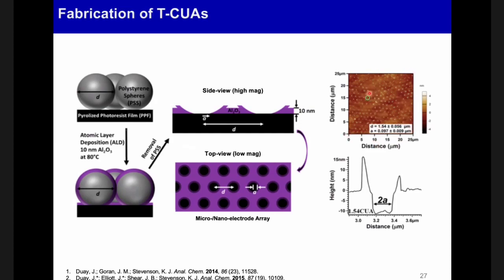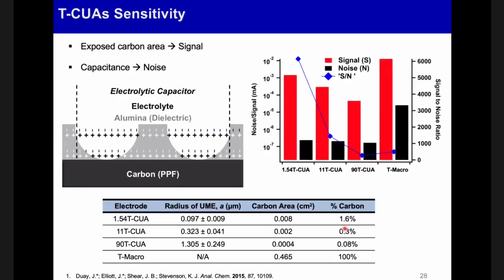So if we take a look at the cross-sectional area of this AFM image, right here, we can determine the radius, which is about 0.097 micrometers. So we're actually down to nanometers, which is pretty exciting. So a lot of people ask me, why do you need spheres? Why can't you just have a plain carbon electrode? And I have this actually on the next slide.